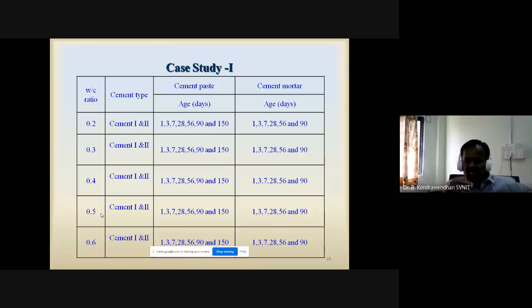We also tested for different ages. One has to see how the pore structure varies over a period of time. That's why we have taken ages of 1 day, 3 days, 28 days, 56, 90, and 150 days for the paste. Whereas in the case of mortar, we stopped the curing age at 90 days. Okay, that's how the initial test was carried out.